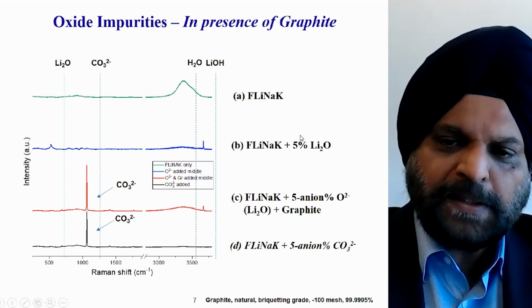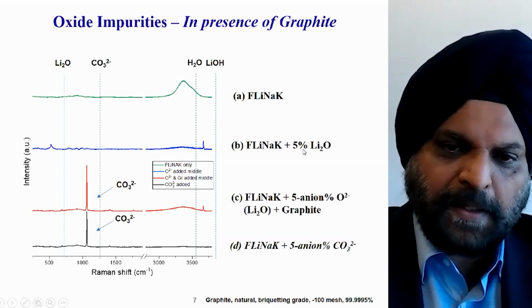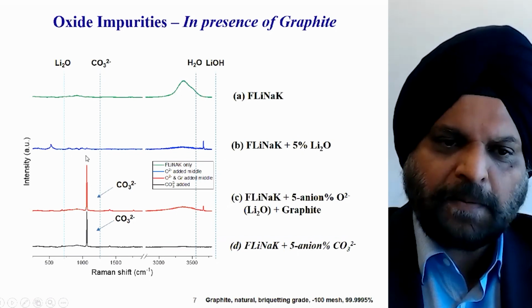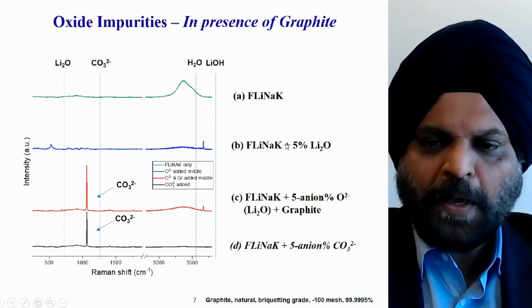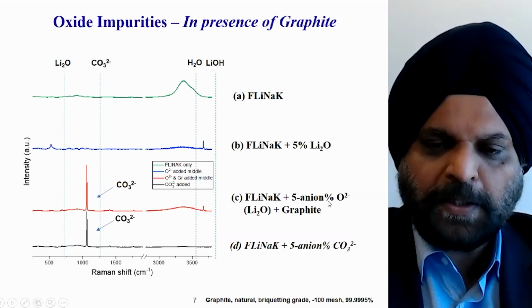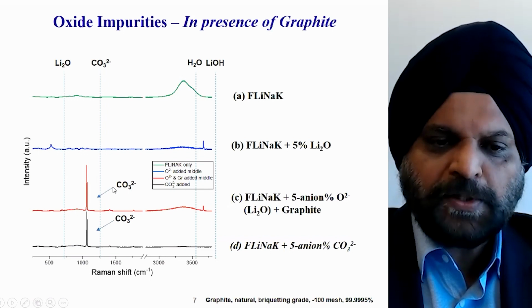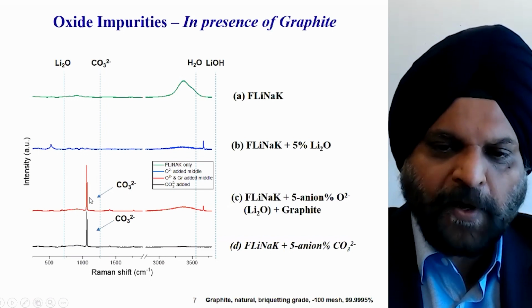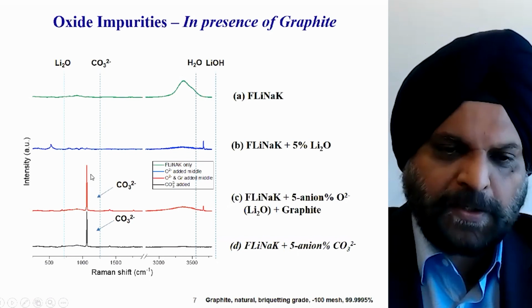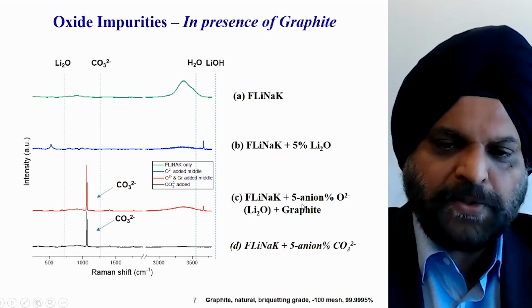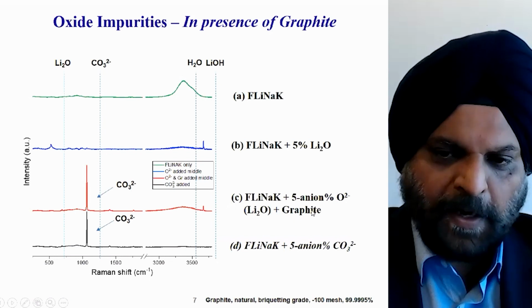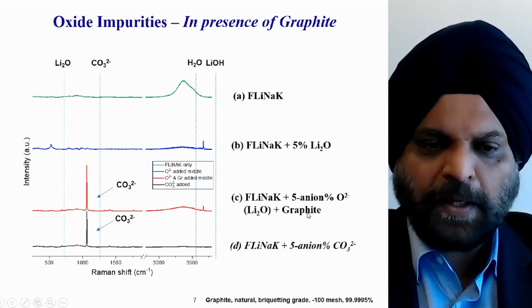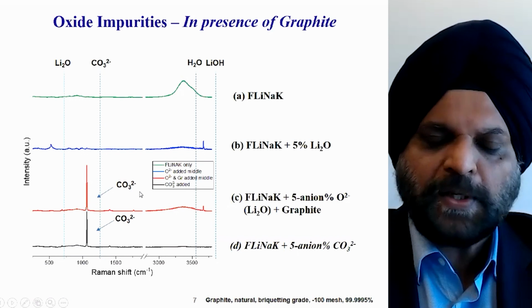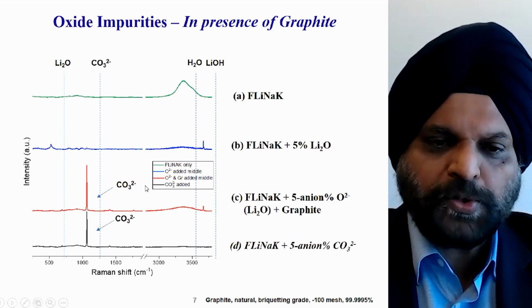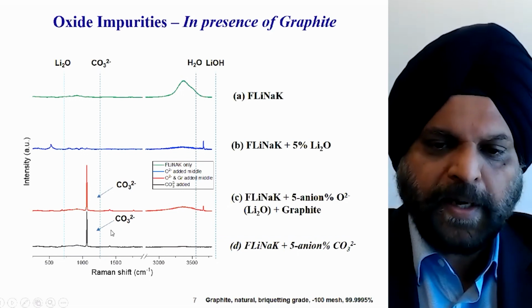If you add simply lithium oxide in there, you still don't see any big change or big Raman peak. But if you now add graphite powder along with lithium oxide, instead of showing a peak for graphite, you actually see a peak for carbonate. So lithium oxide does react with graphite, giving you lithium carbonate, which is soluble in solution. In these tests, we didn't have any metal exposed. These were done in nickel, no other reactive metal.